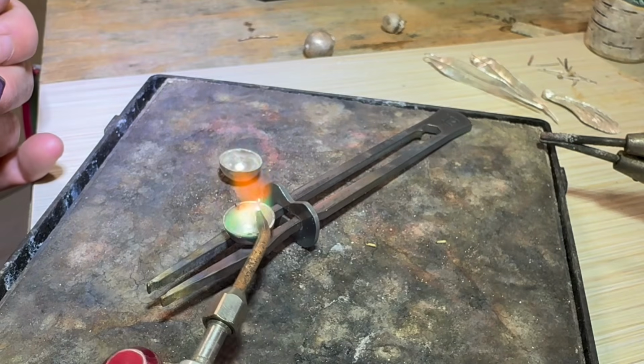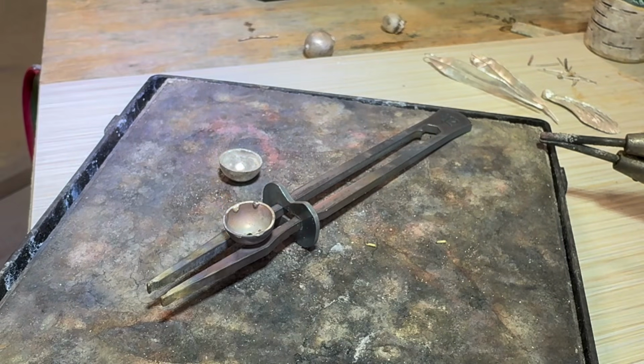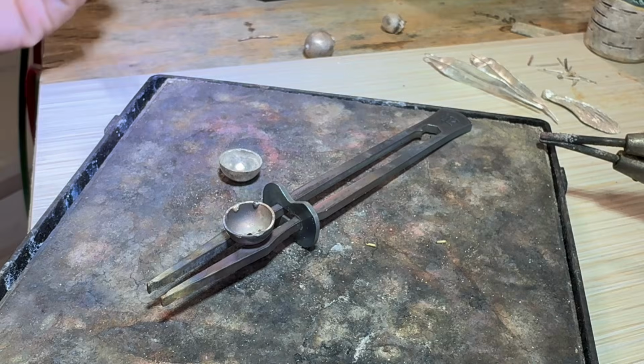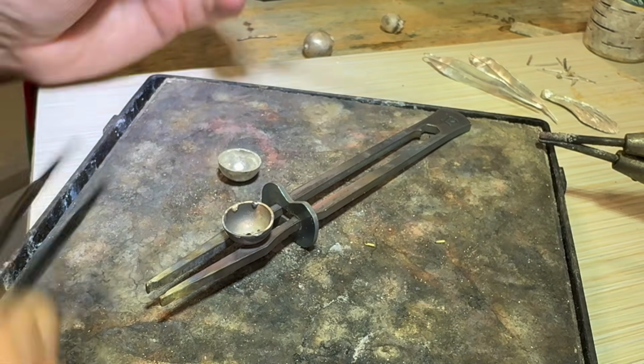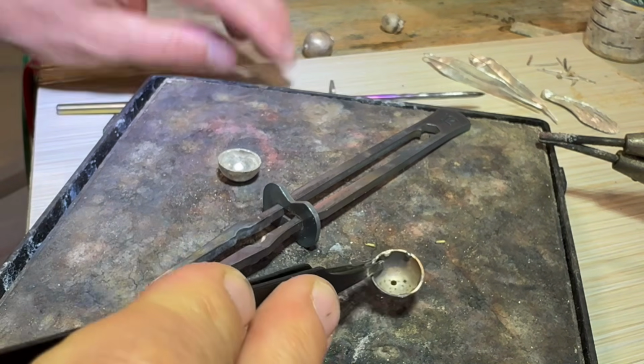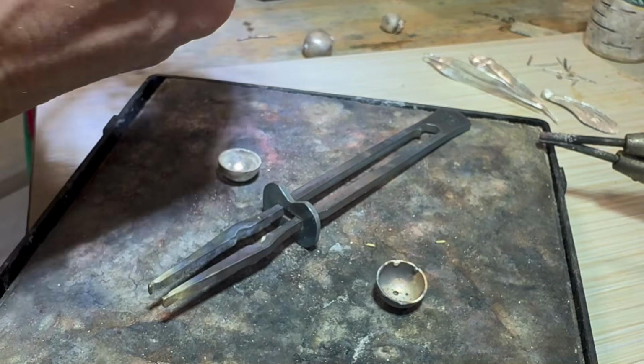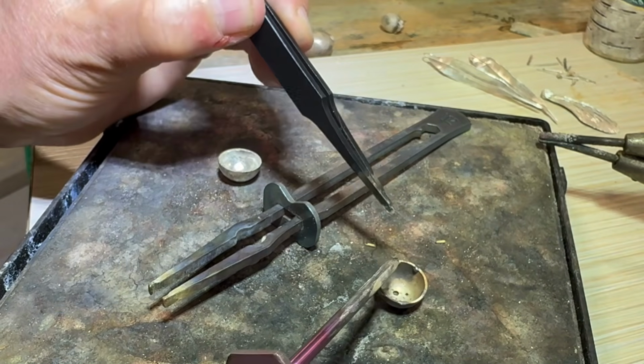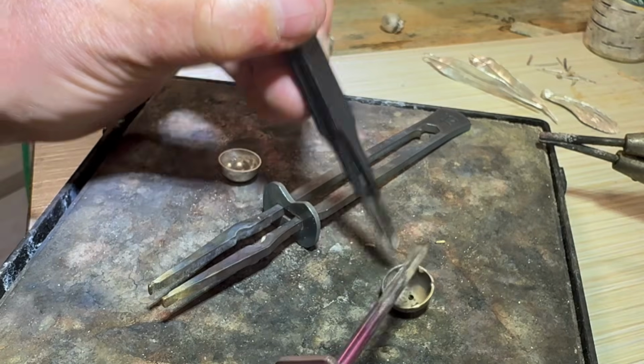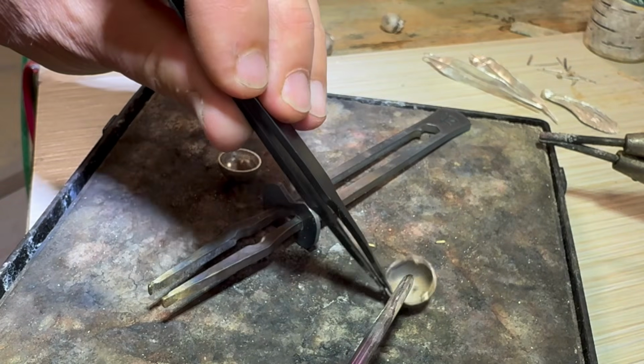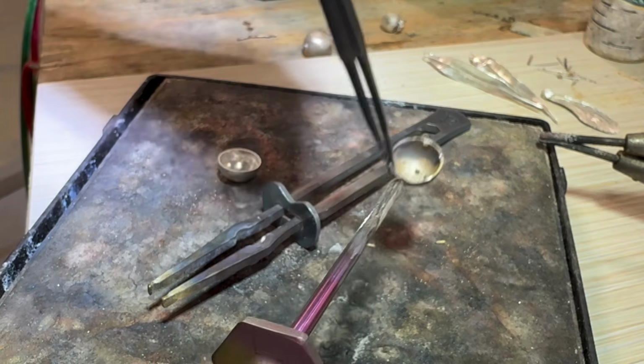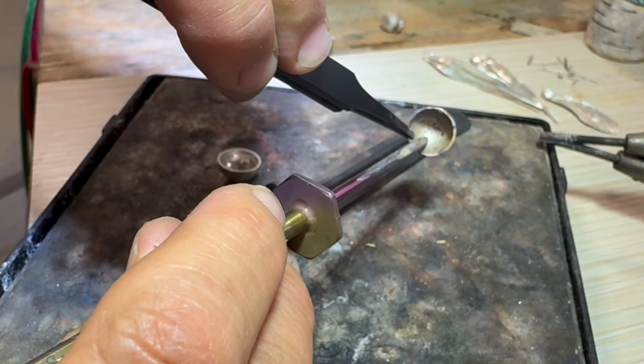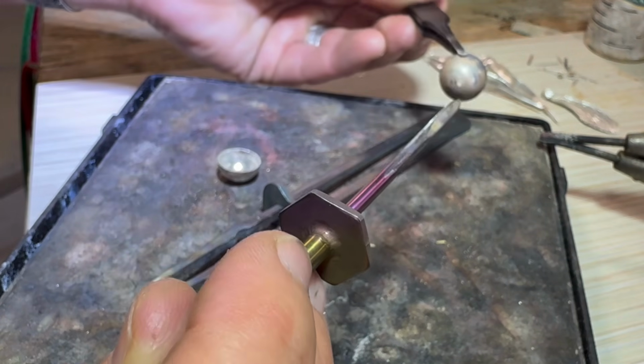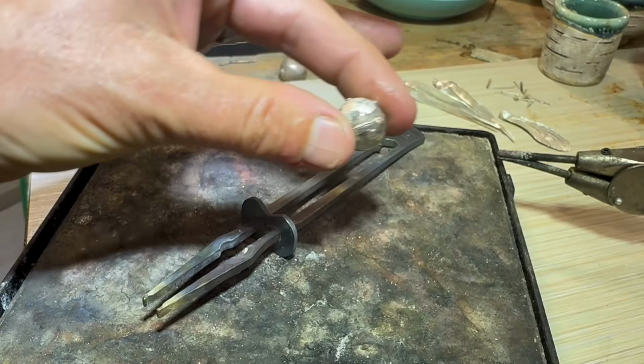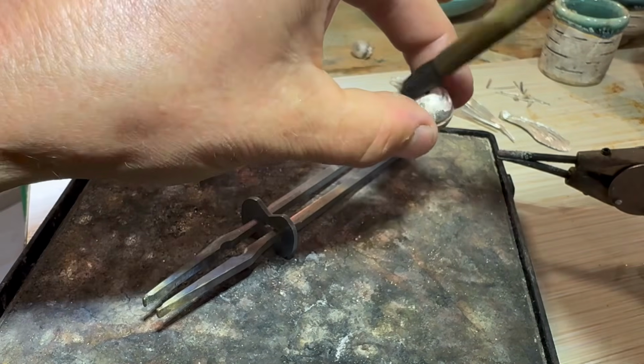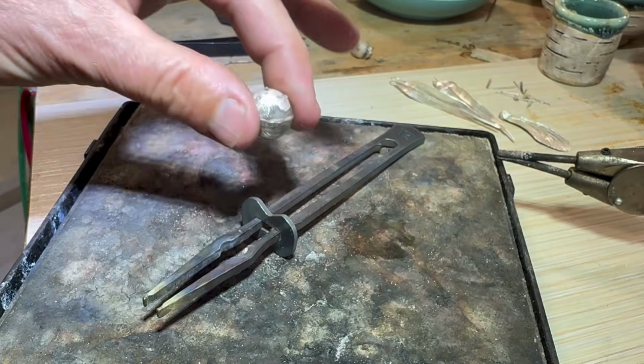Once that's done, I want to show you how to diagnose your silver by color. If you've taken a long time to heat your piece to try to sweat the solder to your metal, you will burn off the flux, in which case your metal will turn black. Black means no more flux. It means that you've oxidized your piece. The yellow means you still have flux in there, and you could still solder to that particular spot if you wanted to. You'll pickle the side that you put the solder on.